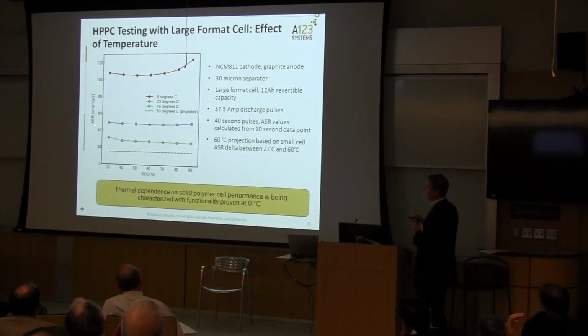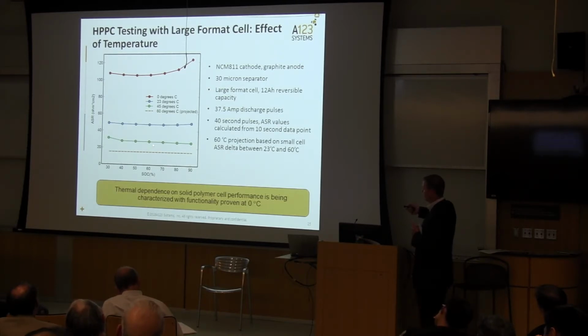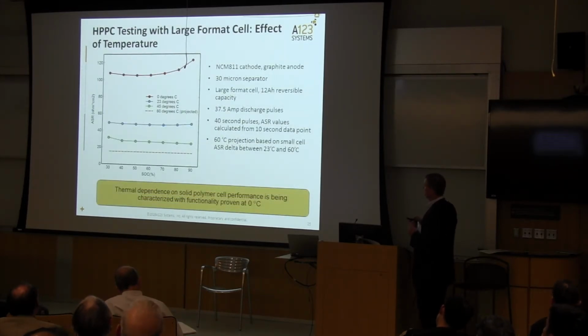And so what you're looking at is the area-specific impedance versus the state of charge of these cells. The fact we actually can get a response at 0 degrees C with a solid-state cell is quite unique. And then as you would expect, as the temperature increases, the impedance reduces. Just to give everybody an idea, this is where you would typically see an 811 cell, just maybe below the 45-degree line. So there's about a 20 to 25 degree C offset in terms of power, and we're working to minimize that gap. So I think I went a few minutes over, so I apologize for that.